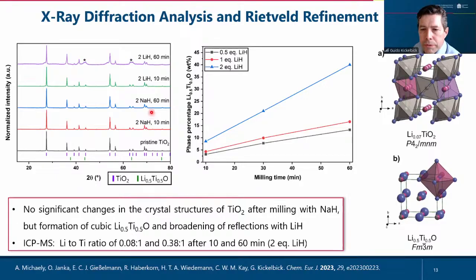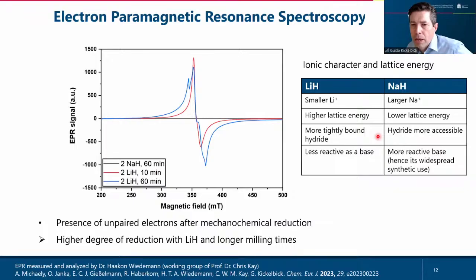What we have detected there is that lithium is intercalating into the titanium lattice. This means that you generate lithium titanate, most likely only at the surface. But we definitely can prove that lithium titanate is present there. Now you can think of why we had these changes in the reactivity, because this is known from the battery business. If you do a reduction and an intercalation, this sometimes helps you in the reduction. So you have two effects, the intercalation and the reduction. If you do both, you can see the reduction. If you can do only one, sometimes the reduction fails.